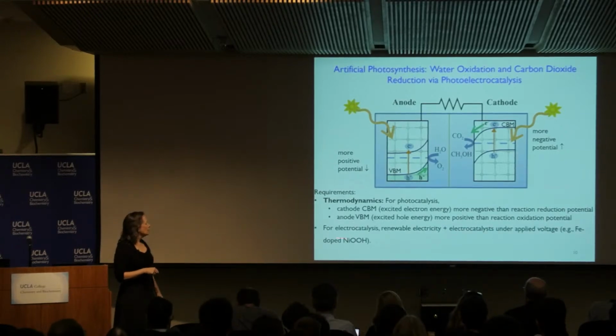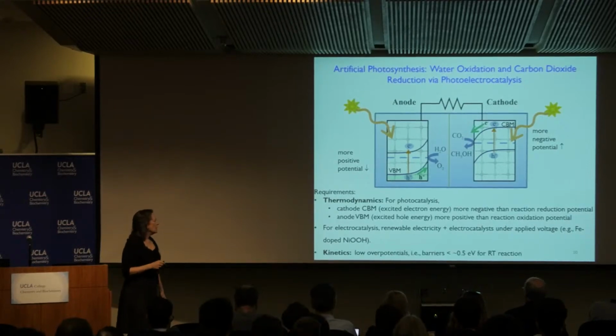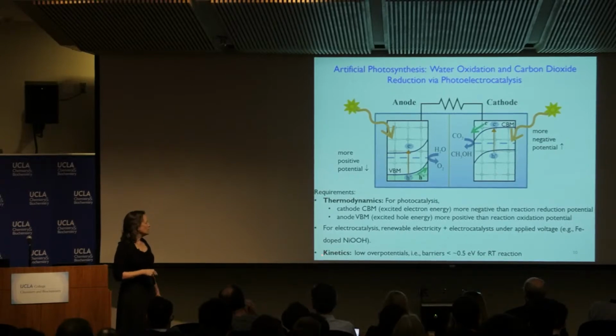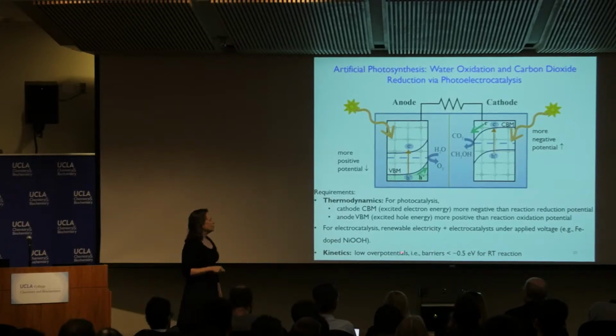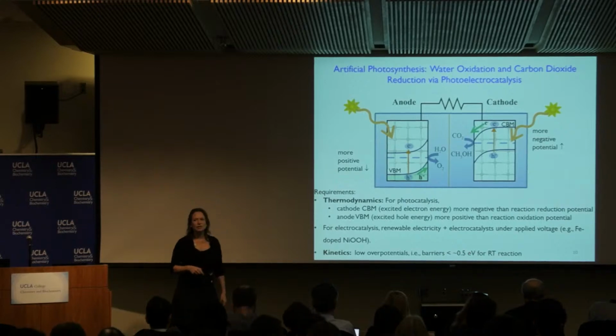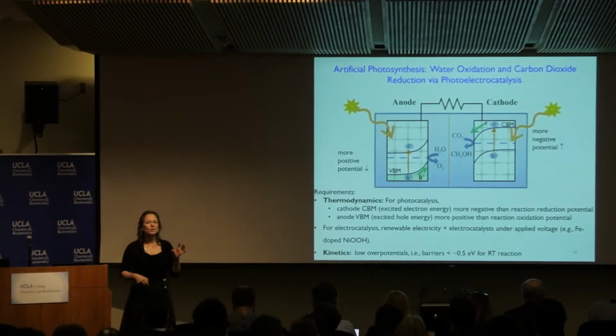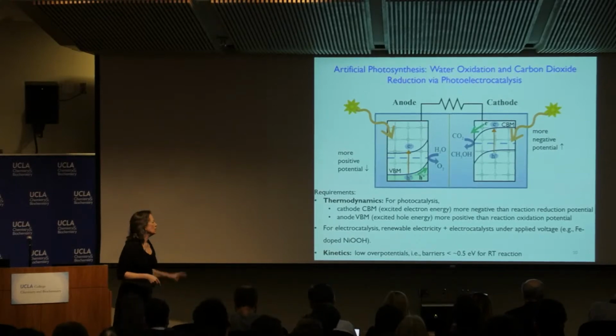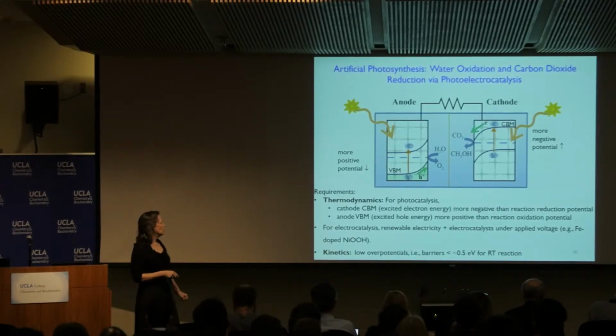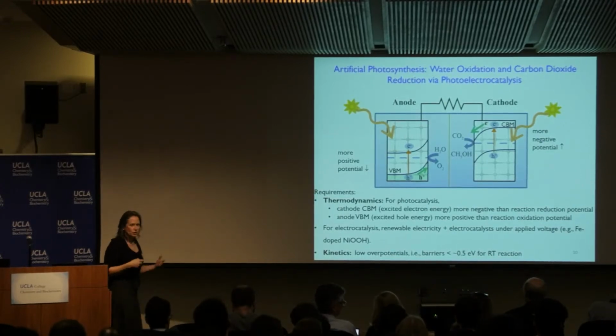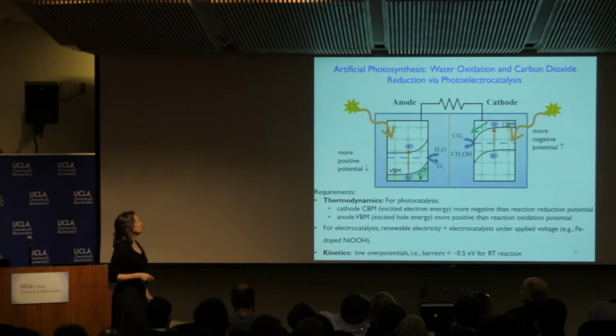As I mentioned already, we've just talked about how to do electrocatalytic water splitting. But what we also need to be thinking about is kinetics, which of course we want these low overpotentials that we've talked about already, and those are associated with the kinetic barriers. In general, we have as a metric that we're looking for reactions that will have a barrier of no more than half an electron volt. So of the order of 10 to 12 kilocalories per mole, 50 kilojoules per mole, at room temperature, so that the reaction can actually go at room temperature. You need something that's a barrier that's not much larger than that.